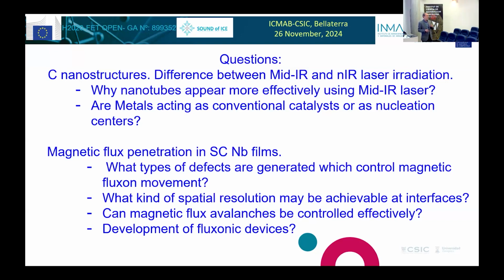I think that they act as nucleation centers because nanotubes stem from the metal sites, and apparently in several studies it has been found that the interface has the carbide of the metal. So it seems that the carbide forms and then the nanotube grows because it nucleates there. But it's not clearly proven.